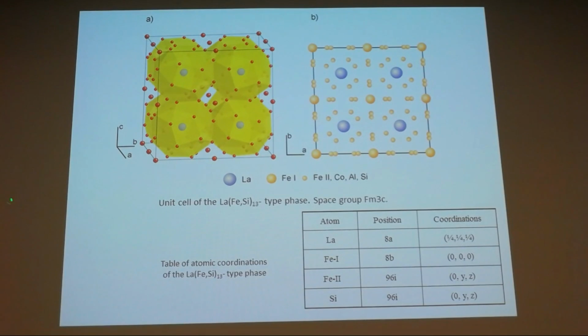We have chosen for our studies this lanthanum iron silicon 13 type phase, and the alloys based on this phase, because it is cheaper than alloys containing gadolinium or pure gadolinium, and also it is easier to tune the Curie temperature for this material by appropriate doping.